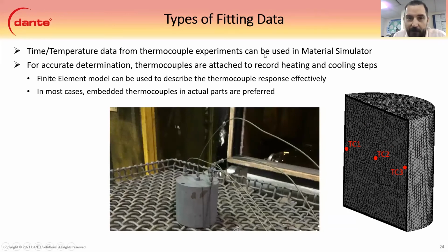So time temperature data, how do we get it? You can use thermocouples. Here we have an experiment that we ran with one of those furnaces. So for the accurate determination, we needed to know what the surface temperature was over time, what the core was over time. And so we use this rig with thermocouples to find that time temperature data. You can use this for pretty much any parts. If you have parts that you're heat treating, you can drill a hole and put it in there. We prefer drilling a hole over attaching them to the surface because you can get like a fin cooling effect with a thermocouple at the surface.